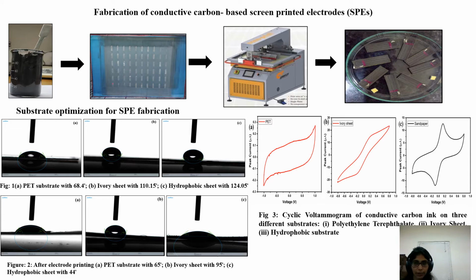For the immunosensor fabrication, my first step includes the fabrication of conductive carbon-based screen printed electrodes. For this, the initial step is the synthesis of conductive carbon ink, which is made using gum arabic and graphite powder in DI water. Thereafter this ink was printed on a hydrophobic substrate using the screen printing stencil and Graphica screen printing machine.